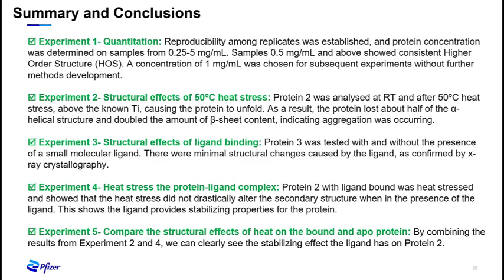In this slide, I'd like to summarize what we discussed today. We discussed 5 experiments, with the first being a simple experiment looking at quantitation of a protein. In this experiment, we were able to establish the reproducibility among replicates, and protein concentration was determined on samples from 0.25 mg per ml up to 5 mg per ml. Samples at half mg per ml and above showed consistent higher order structure. And as a result, a concentration of 1 mg per ml was chosen for subsequent experiments without further method development.